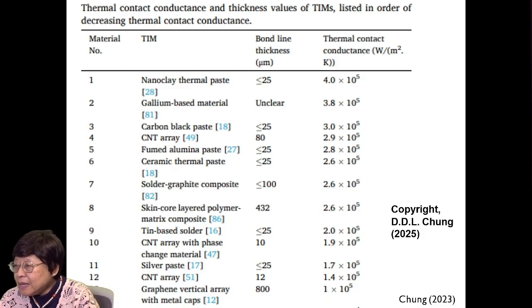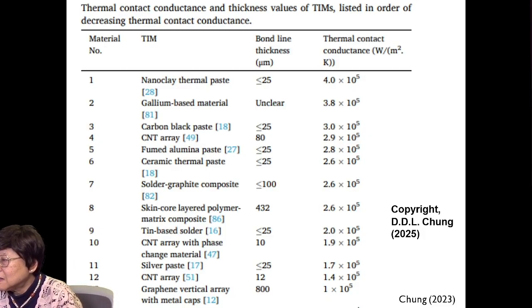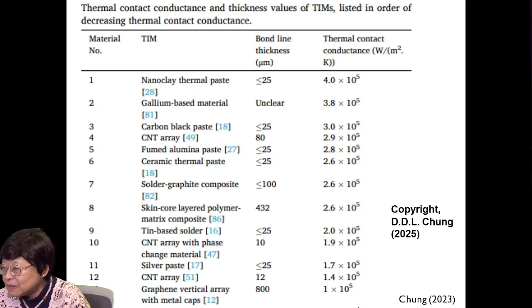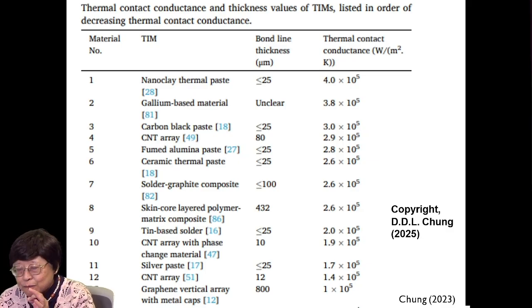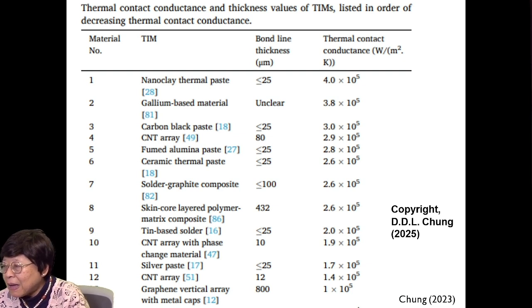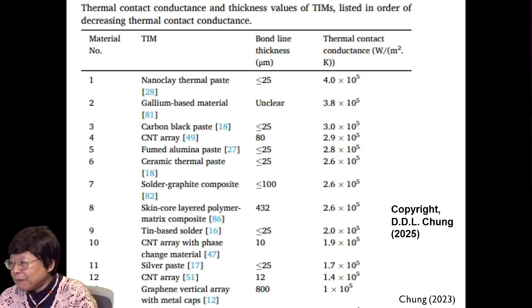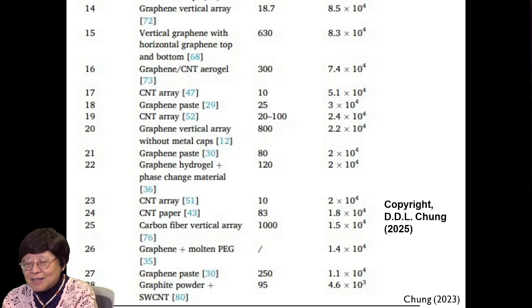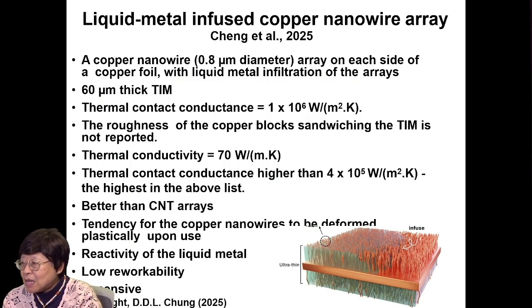Here is a list of the thermal contact conductance and thickness values of TIMs, listed in order of decreasing thermal contact conductance. The nanoclay thermal paste is at the very top, followed by gallium-based material, carbon black paste, CNT array, fumed alumina paste, ceramic thermal paste, solder graphite composite, and so on. And it goes on. The lower the list, the worse it is.